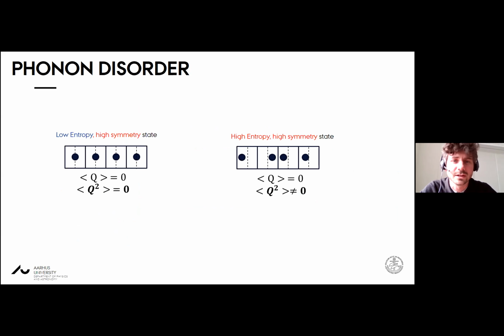in the phonon situation here, I just show the two cases of the possible high temperature phase of vanadium dioxide. One is the low entropy, high symmetry state, in which I started from at the beginning, where I drew all the atoms in the high symmetry position. And on the right-hand side, I show the disordered case, where there's still no net distortion in the system. It's hard to show that with only 4 atoms. So you have to imagine a larger system in which there is zero average displacement from the high symmetry place. But now you can represent the displacements by a non-zero Q squared. So the high entropy state has a finite Q squared, whereas the low entropy state has zero Q squared. So not only is the average position zero, but the displacements are zero.